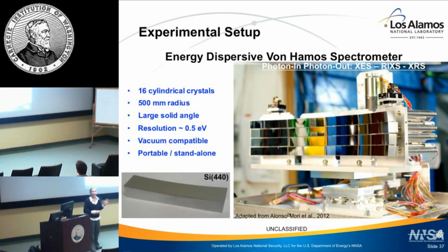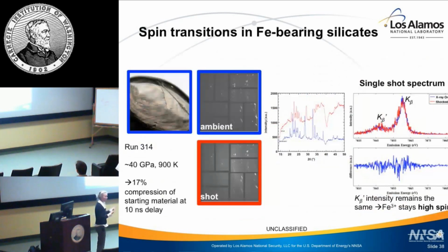So here we are, an iron-bearing silicate, so-called hypersthene, so it's essentially an iron-bearing pyroxene at ambient condition. I'm sorry, this is a little hard to see, but we have our pyroxene crystalline structure. I'm going to shock compress up to these conditions, about 40 GPa, 900 K. In the diffraction, I just see some compression, about 17% compression. This is my shot or my compressed image.